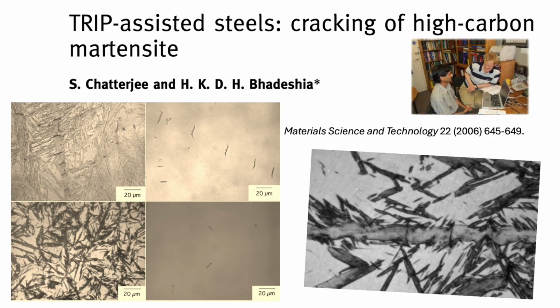And where does this transformation happen first? Usually at the surface, because that's where the temperature drops low enough first to trigger the martensite transformation, for example. So you get expansion starting at the surface, generating tensile stress there, right when it might already be in thermal stress. Potentially, yes. It gets complicated, and the two stress types interact. High hardenability, meaning martensite forms easily, can actually sometimes make things worse from a stress perspective if it forms at the wrong time or place. So you've got thermal shrinking and expanding, plus phase change expanding. Yeah. It's a recipe for disaster.